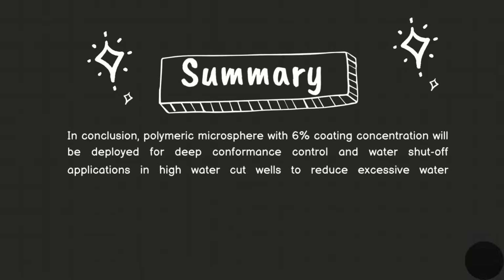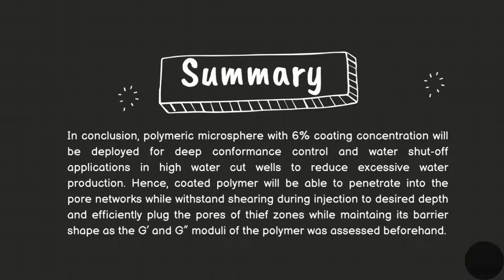In conclusion, polymeric microsphere with 6% coating concentration will be deployed for deep conformance control and water shut-off applications in high water cut wells to reduce excessive water production. Hence, the coated polymer will be able to penetrate into the pore networks while withstanding shearing during injection to the desired depth and efficiently plug the pores of the thief zone while maintaining its barrier shape, as the G' and G" moduli of the polymer were assessed beforehand.